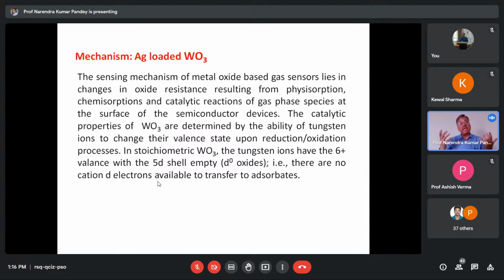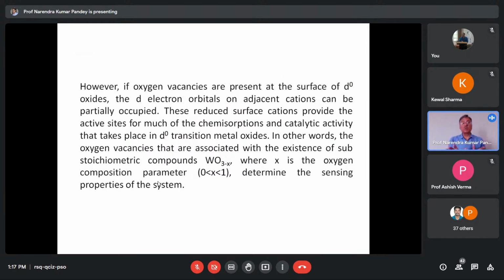What exactly happens if Ag is loaded to WO3? The sensing mechanism of metal oxide based gas sensors lies in the change in oxide resistance resulting from physisorption, chemisorption, and catalytic reactions of gas phase species at the surface of the semiconductor device. The catalytic properties of WO3 are determined by the ability of the tungsten ions to change their valence state upon reduction. In a stoichiometric WO3, the tungsten has 6 plus valence with 5d shell empty. There are no cations. Now, this is how the stoichiometry changes when Ag is added. I will not go into the chemistry of this one right now.